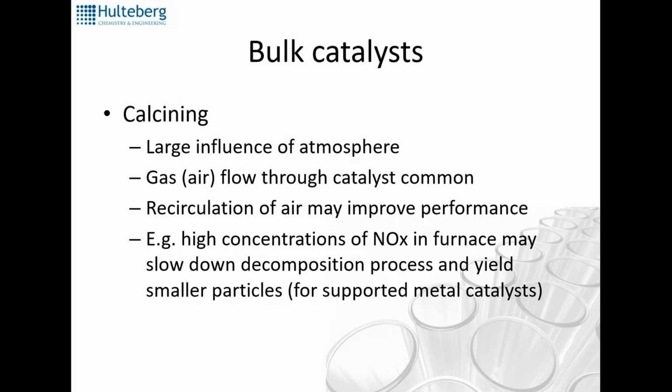For that reason, there might also be recirculation, and recirculation is not only for recovering the heat. If you, for instance, have high concentrations of NOx built up in the system, the NOx buildup might actually slow down the decomposition process, and that might actually yield smaller particles. And now we're talking supported metal catalyst, but there are these influences of the calcination environment.